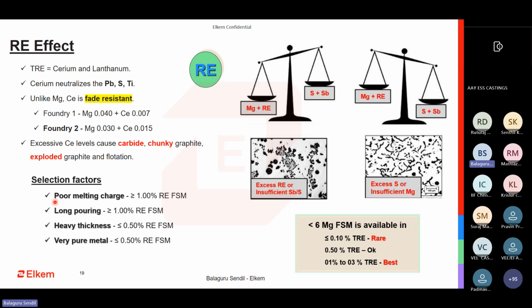So the ideal combination is that I have a 6% magnesium. Less than 0.1 rare earth is very rare. 0.5 rare earth is okay. If I have 1 to 3% rare earth with 6% magnesium, it is ideal. Less than 6% is an ideal combination from the casting yield point of view.